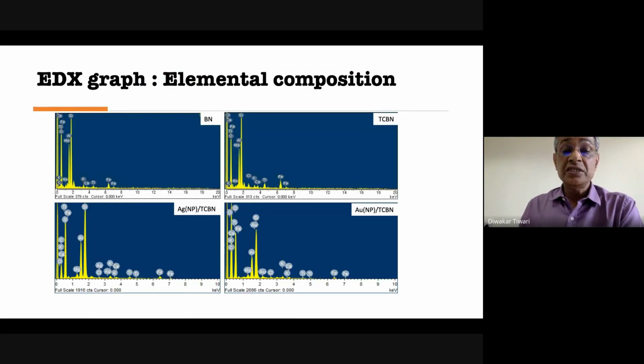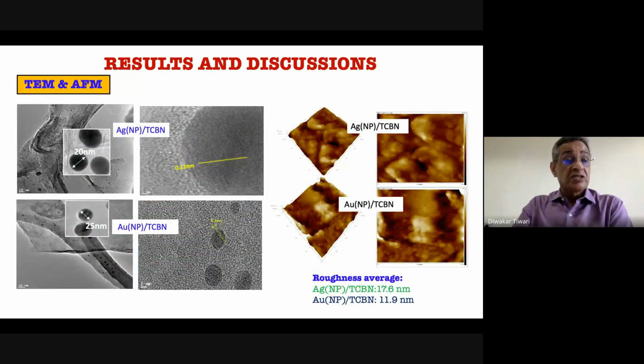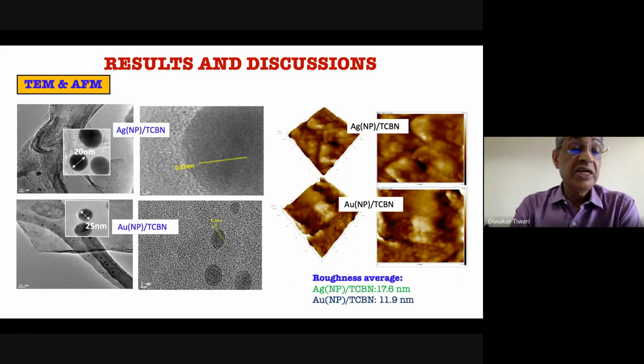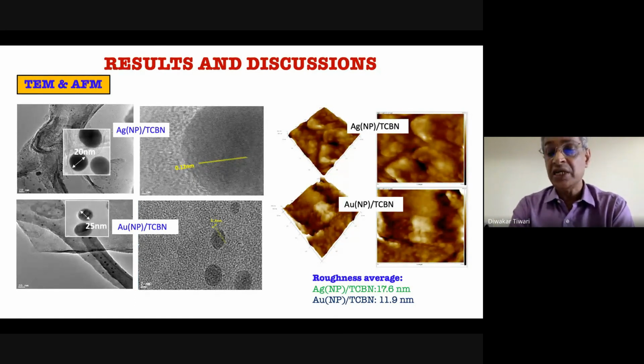With the EDX data, we confirmed the silver and gold peaks in the spectra, which confirmed that silver and gold have been impregnated, or decorated, on the surface. So these are the TEM images we could get, and we have also confirmed with the XRD data that the silver or gold nanoparticles are aggregated, with an average nanoparticle size somewhere around 20 to 25 nanometers.